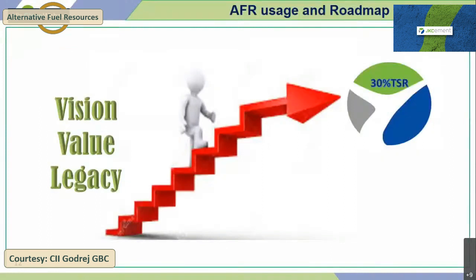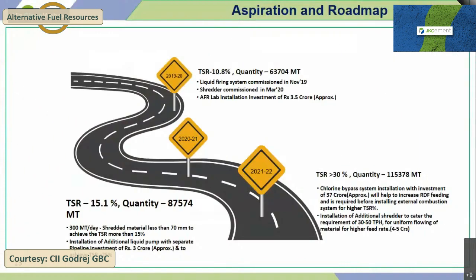About our AFR usage and roadmap, we have a roadmap to achieve 30% TSR in the near future. Last year, in 2019-20, we achieved a TSR of 10.8% with a quantity of 63,704 tons, in which we commissioned the liquid AFR system and the shredder. We commissioned the imported shredder in March 2020 and installed the AFR lab. After that, in 2020-21, we achieved a TSR of around 15.1% with a total quantity of around 87,000 tons, in which we were able to shred the material properly, and we utilize 300 metric tons per day of shredded material.